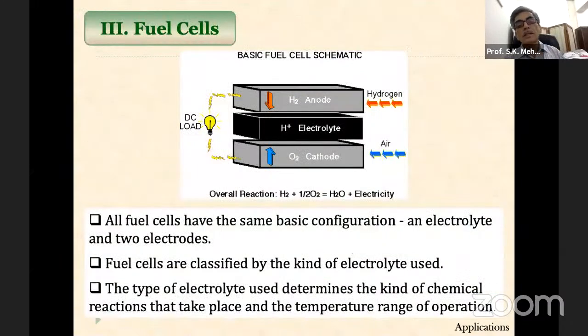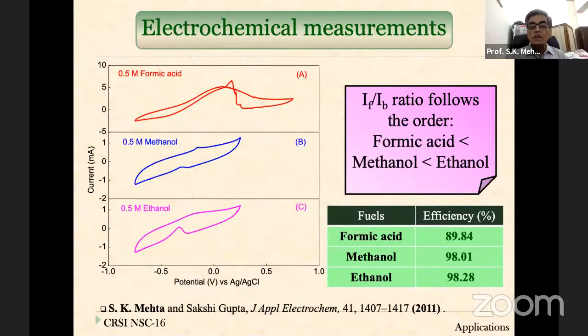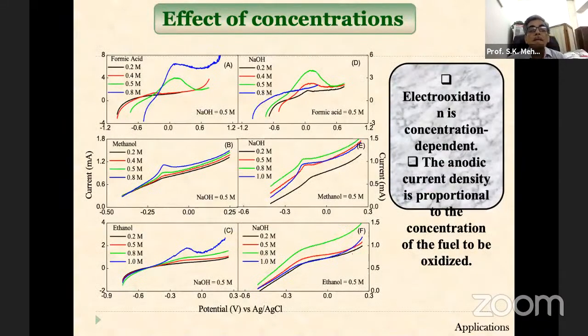Then we also did some work on fuel cells, and again I'll skip this. We used this for understanding, having the fuels as formic acid, methanol, and ethanol, and we could achieve efficiencies of 89.84, 98.01, and 98.28. So the cyclic voltammetry graphs you can see, and potential versus current we mapped, and again we can vary the effect of concentration of NaOH, formic acid, methanol, ethanol, and we found that electrooxidation is concentration dependent, and the current density is proportional to the concentration of the fuel.